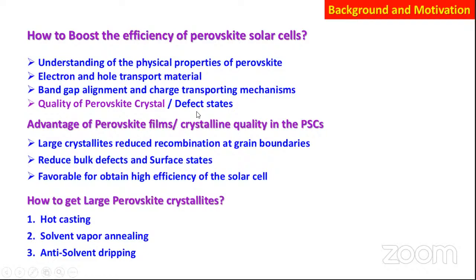One of the main key factors to get high efficiency is larger crystals, because they reduce the recombination at the grain boundaries, resulting in reduced bulk defects as well as increased efficiency of the solar cell. Now, how do we get larger perovskite crystals? There are many methods available, like hot casting, solvent vapor annealing, and anti-solvent dripping.